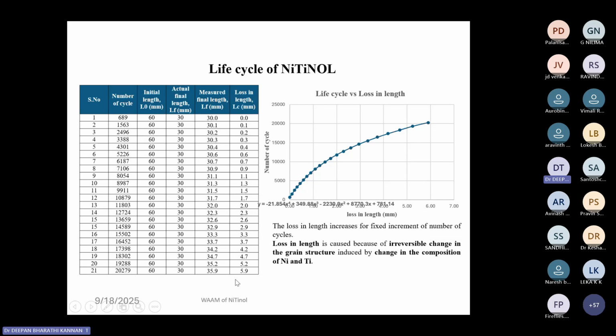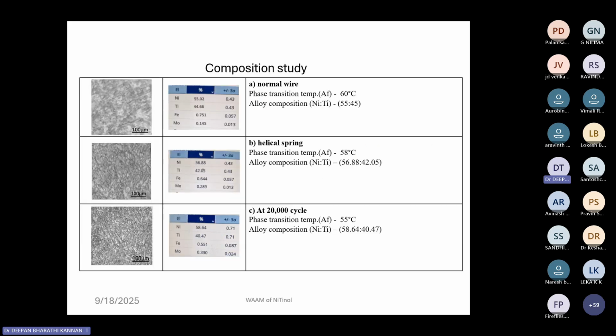Because of some metallurgical changes happening due to the continuous supply of heat, the students are observing a slight loss in length with respect to the shape memory effect. They were also noticing some change in the phase transformation temperature. The initial phase transformation temperature, that is AF, was around 60 degrees Celsius. For the helical spring, after the shape setting, it shifted to 58 degrees Celsius. You could see that the nickel content initially was around 55 and the titanium was 45. After that heat treatment for a certain time, the nickel and titanium contents obviously change, to around 56.88 and 42.05 for titanium in the helical spring.